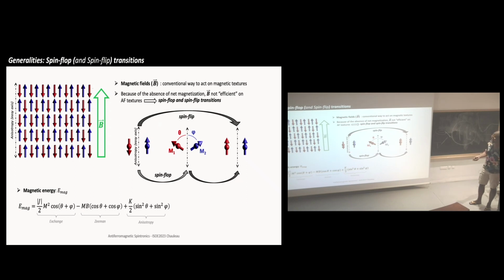If you consider the magnetic energy, you can directly evaluate at what field this transition will happen. So let me explain shortly what those 2 transitions are. If you take what we call an easy-axis antiferromagnet, that means that there is only one axis in which direction the spin wants to lie. We will come back to that a bit later. But the spins are lying in that direction, either up or down. This is the antiferromagnet. So the first transition is called the spin flop.